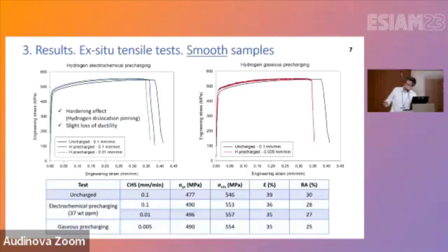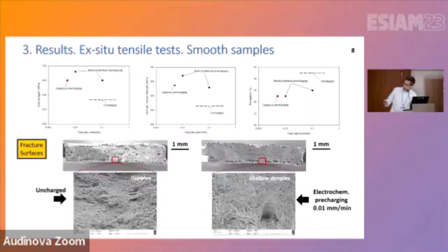Regarding the tensile behavior, in the case of the smooth samples, we evaluate hydrogen embrittlement susceptibility after the electrochemical, left side, and gaseous precharging at different crosshead speeds. Based on these results, we can say that hydrogen induces hardening. This fact could be associated with the hydrogen dislocation pinning mechanism, and hydrogen promotes a slight loss of ductility based on elongation and reduction of area. We can see this in both cases, independently of the precharging methodology.